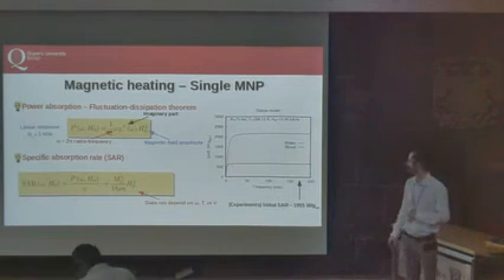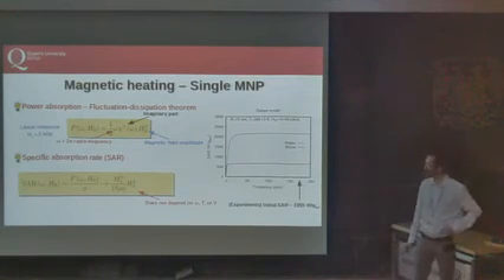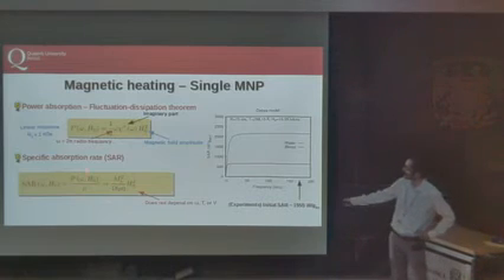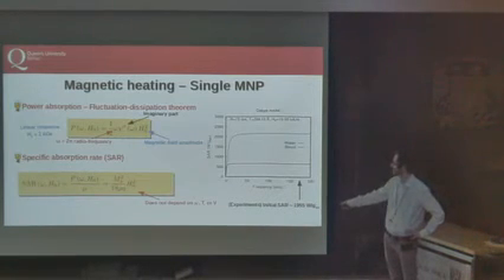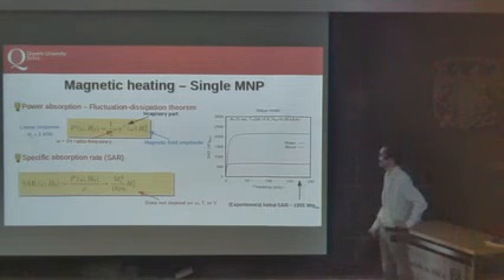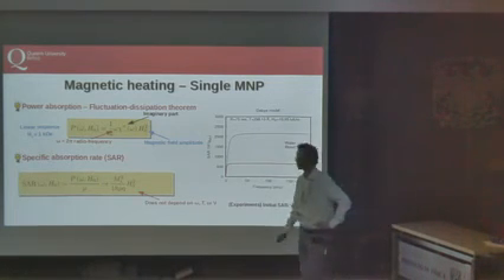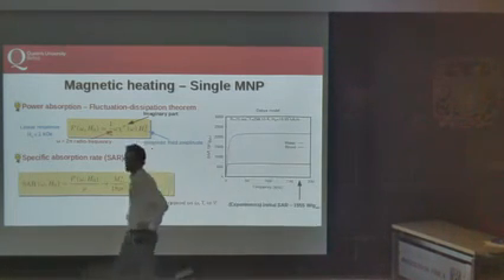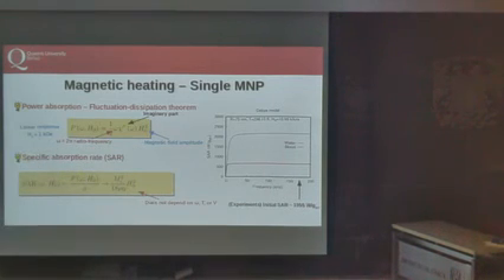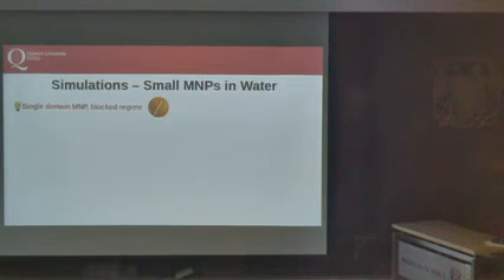If I substitute the numbers for the Brownian relaxation time, you see that we have an expression which is in fact independent of frequency, temperature, and volume. I want to stress this is true if we neglect Néel relaxation. 5 minutes, wow. Néel relaxation, so for very small nanoparticles. So let me go quickly to the simulation of small nanoparticles in water.